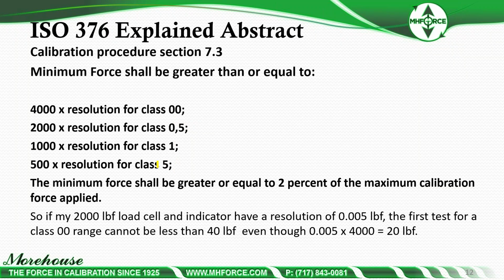I made a mistake there, that should be class 2, 500 for class 2. The minimum force shall also be greater than or equal to 2% of the maximum calibration force applied. So if I have a 2,000-pound load cell and indicator with a resolution of, let's say, 0.005 pounds, the first test for the class 00 range cannot be less than 40 pounds, which is 2%, even though 0.005 times 4,000 equals 20 pounds.